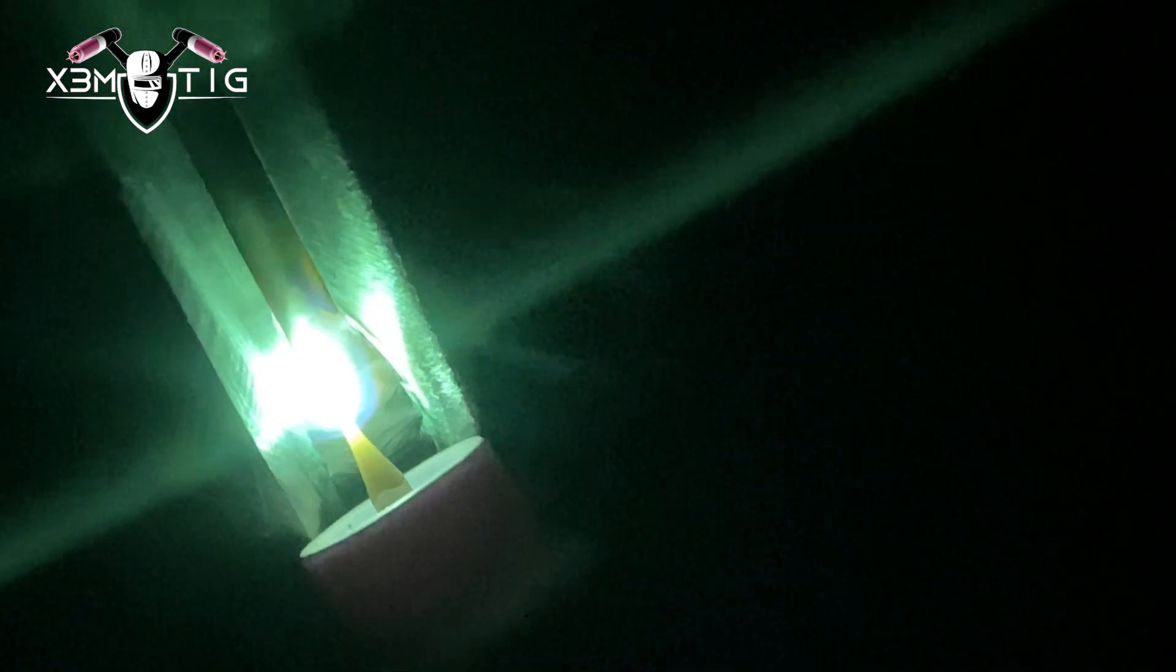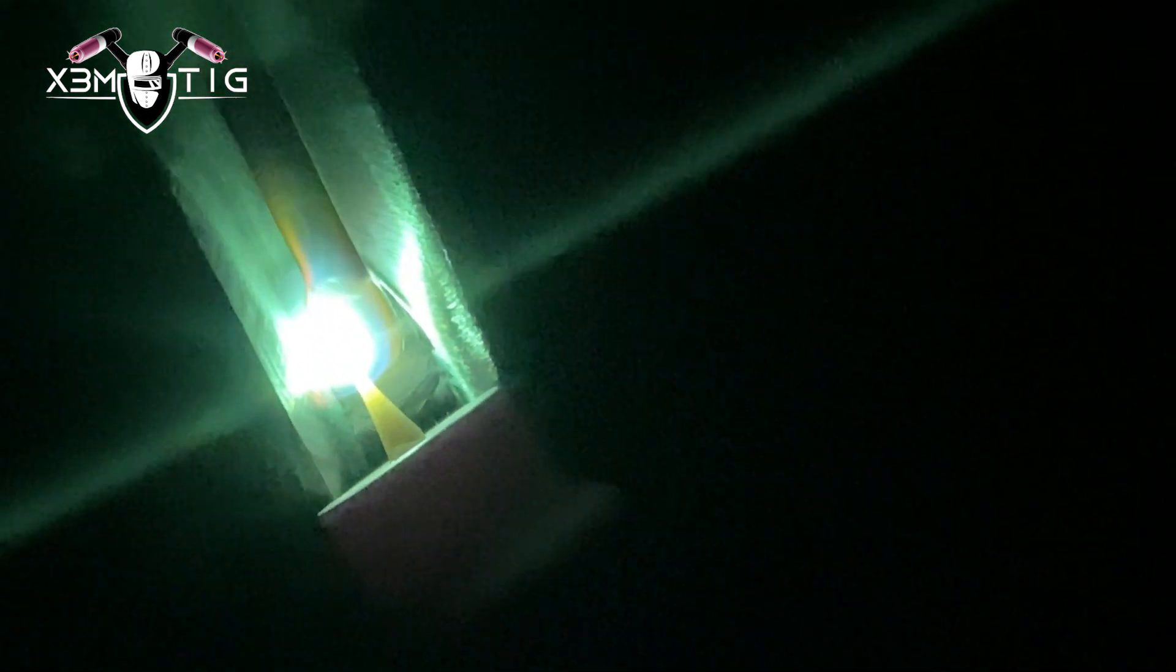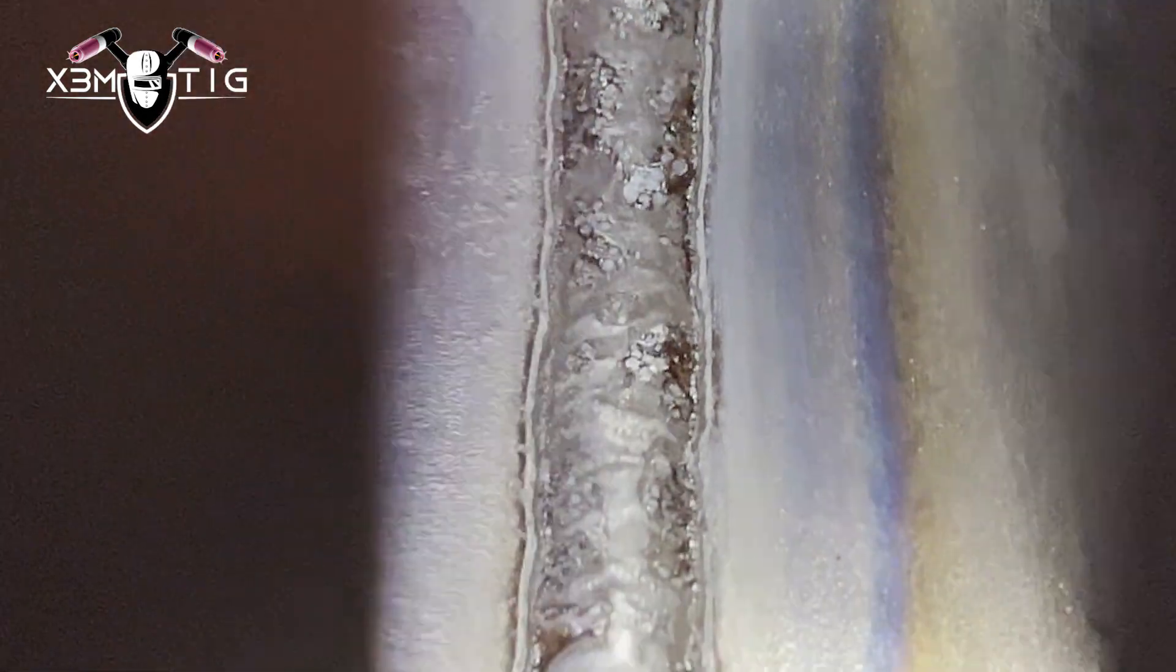Keep it, be consistent. Just try to keep that rod inside. You gotta be careful with that tungsten inclination. If you put a little bit of upper angle, then you're gonna burn that rod. It's gonna stay cold, it's gonna stub. You want to burn on the bottom of that rod and just keep it inside. Don't try to lose any connection with your puddle. That's the solid root I got and I like it like that. Once you got solid root, you don't have to worry.